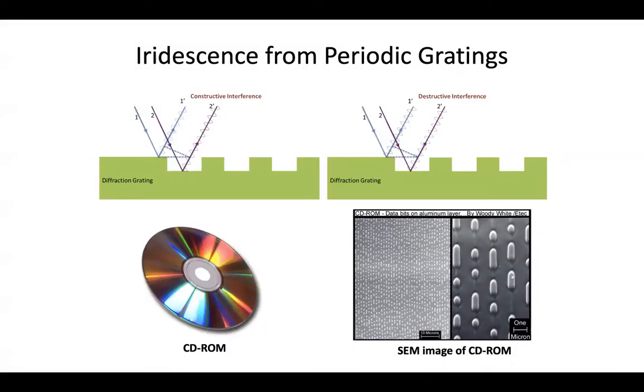Kind of a related situation is when instead of a thin film on a substrate, you just have periodic gratings. It turns out that the mathematical formalism is identical to what happens when you have a thin film. So a CD-ROM is like the perfect example. The information in a CD-ROM is encoded through pits with an aluminum layer. And so those rays of light that are going to reflect off of the aluminum will have to interfere in a totally constructive fashion with those rays of light that are reflecting off the bottoms of the pits in order to achieve a certain kind of color. And so it's the same n lambda equals 2d sine theta formulation. And that's why the backside of a CD-ROM shows that beautiful rainbow effect.